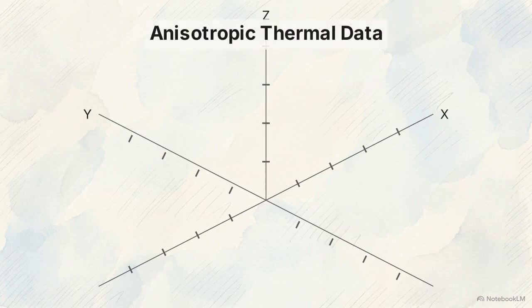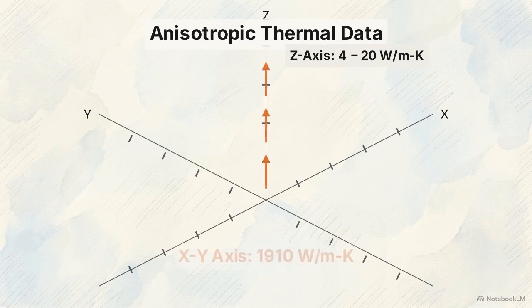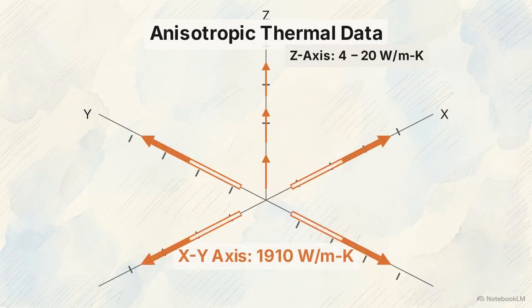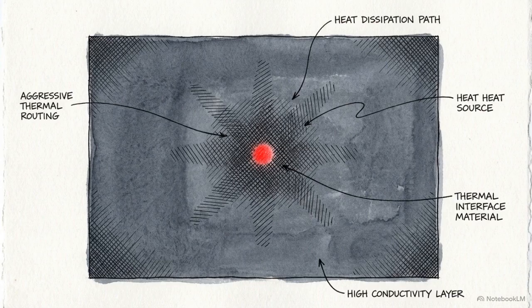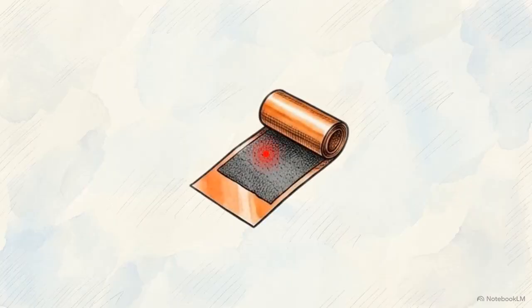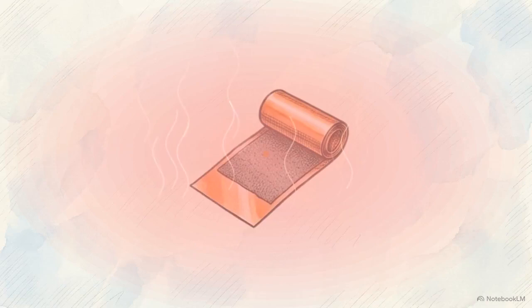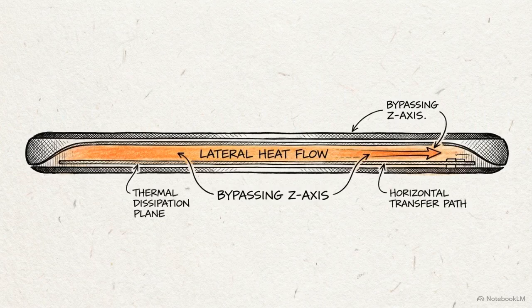This vector chart represents the material's anisotropic thermal data. Vertically, along the Z-axis, the thermal conductivity sits between a standard 4 and 20 watts per meter Kelvin, revealing the critical metric. The horizontal XY axis thermal conductivity reaches 1,910 watts per meter Kelvin. The functional result of this disparity is aggressive thermal routing. A pinpoint localized heat source is instantly stripped of thermal energy, spreading it rapidly across the entire wide surface area of the sheet for passive convective cooling. Artificially manipulating the directional flow of heat allows engineers to bypass physical Z-axis space limitations entirely.